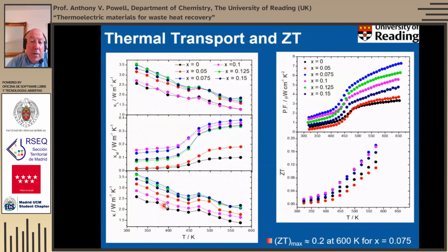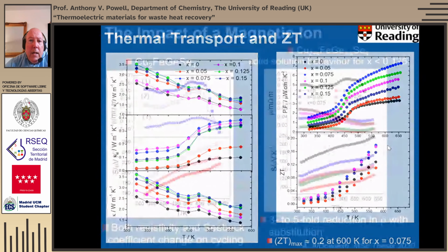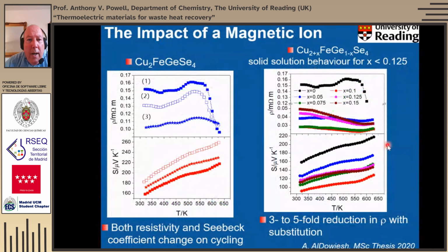The thermal conductivity is also increased, principally because of the changes in the electrical contribution, which are shown here. But nonetheless, this increase in the power factor is sufficient to increase the ZT slightly, and we get up to about 0.2 at 600 Kelvin. So then we thought, well, what happens if we replace that zinc with a magnetic ion?